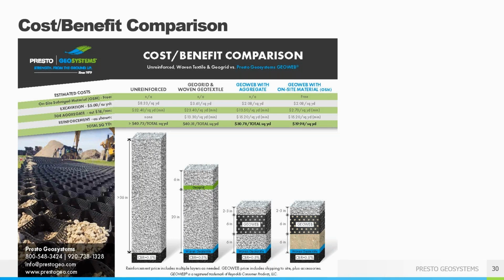You can see the GeoWeb system provides both thinner and less expensive cross sections, significantly so when on-site material is used. We assumed an aggregate cost of $18 a ton, and this had the unreinforced section coming in at $41 a square yard. The geogrid geotextile section at about $40 a square yard. The GeoWeb with imported aggregate at $31 a square yard. And if you have on-site material that can be used, you're all the way down to $20 a square yard. Less than half the cost of an unreinforced section.